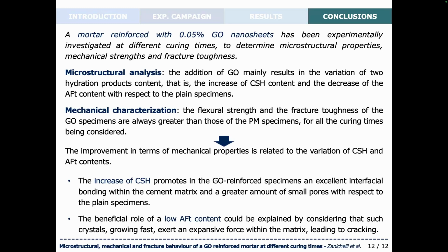And as far as the mechanical characterization is concerned, the flexural strength and the fracture toughness of the GO specimens have been found to be always greater than those of the PM ones for all the curing times analyzed, and then to stabilize after 90 days of curing. So we can conclude that the improvement that we observed in terms of mechanical properties can be related to the variation of the amorphous phase and of the ettringite contents.